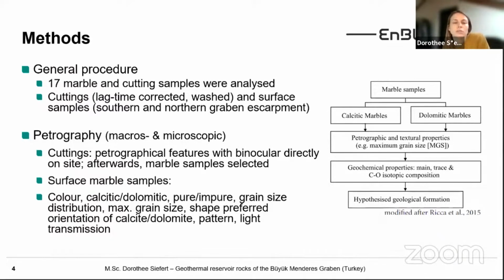and macroscopic characterization we did of color, rock texture, including shape, preferred orientation, pattern, grain shape, structure, as I said, maximum grain size and grain size distribution of the calcite and dolomite grains, and open or sealed fissures and possible weathering features in the field on the hand specimens of the surface samples. And for the cutting samples, these investigations were carried out using the binocular, and microscopic features were analyzed at the drilling site, as just mentioned.